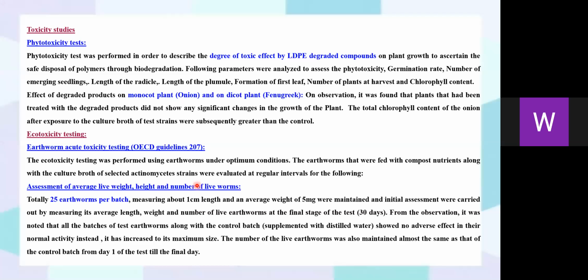In total, 25 earthworms were measured up to about 1 centimeter in length, and an average weight of 5 mg was maintained. From the observation, it was noted that all the batches of test earthworms along with the control batch showed no adverse effect in normal activity. Instead, they increased to their maximum size. The number of live earthworms was also maintained almost the same as that of the control batch from day 1 of the test till the final day.